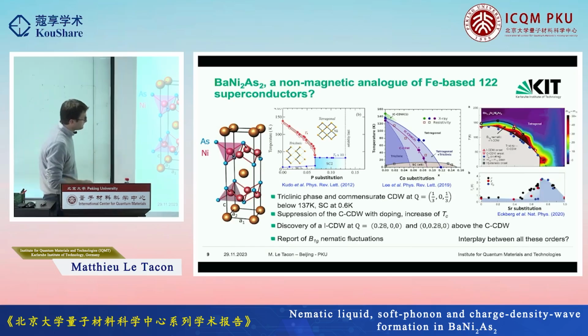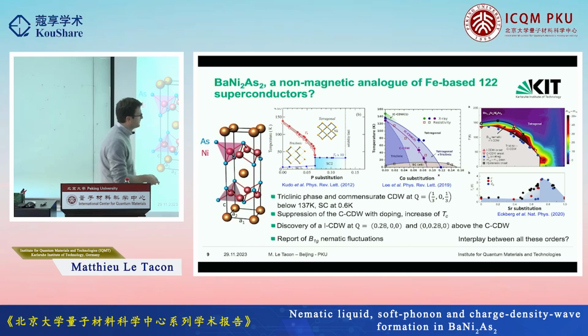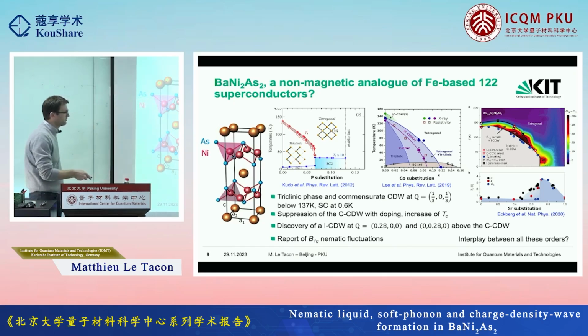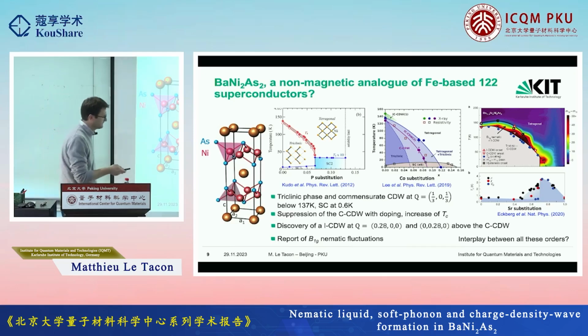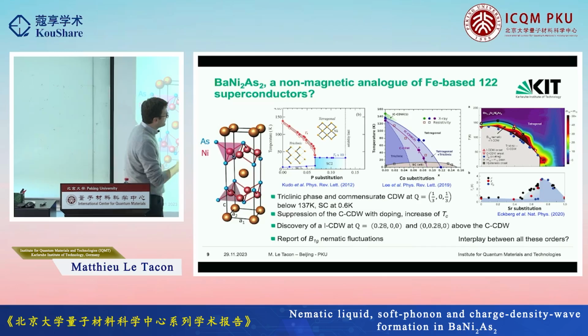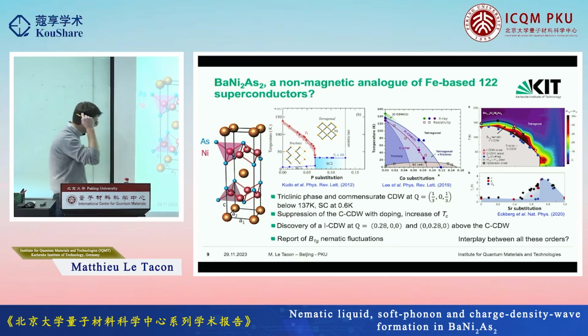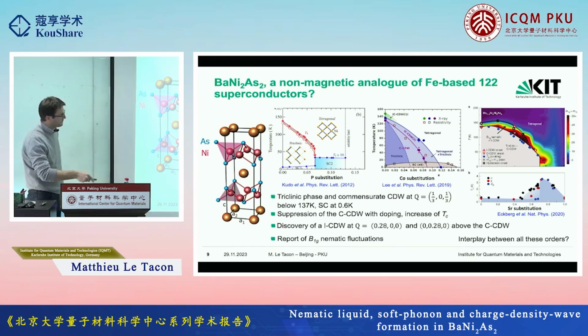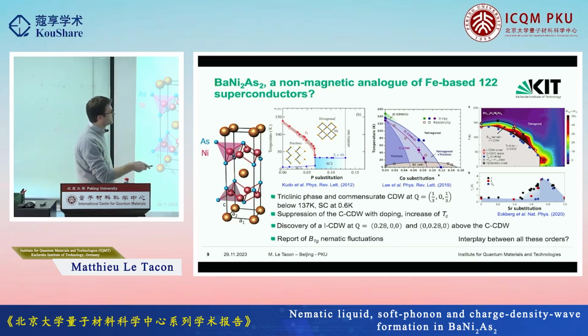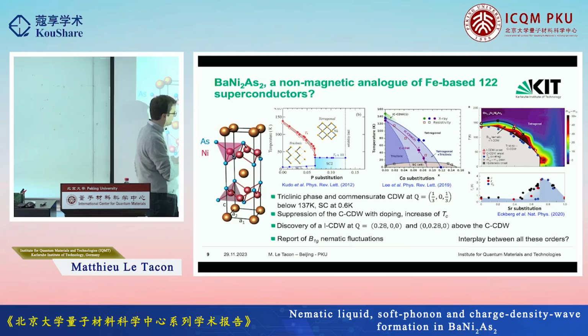And associated with that, there's been a report of nematic fluctuations, but now of B1g symmetry, so rotated by 45 degrees compared to the iron-based superconductors. So this has been looked at with different probes, and one thing that is striking is that all those phase diagrams look a bit different, with strontium substitution, cobalt substitution, phosphorus substitution. And I guess what we try to understand is the interplay between all those: the charge order, the nematicity, the superconductivity.